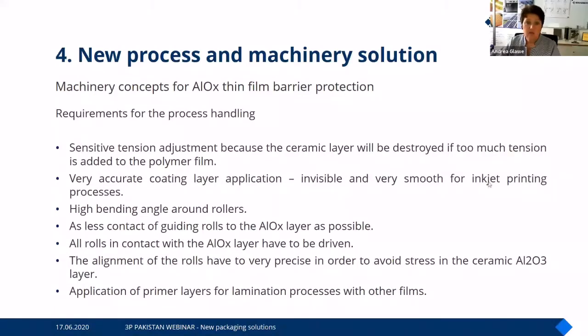What is necessary in such an aluminium oxide coating line? The material AlOx is a ceramic layer, and I guess you can imagine ceramic is very sensitive. So we need to look into a very sensitive handling of the material. It's necessary to have a very perfect coating layer, usually invisible and very smooth, to realize, for instance, inkjet printing processes. We need to go with a high bending angle around rollers to avoid that the AlOx layers start to crack or get certain kinds of problems.